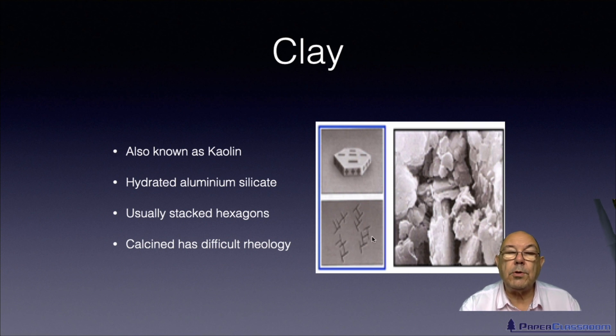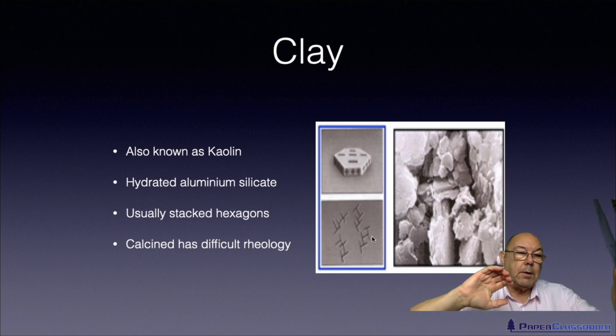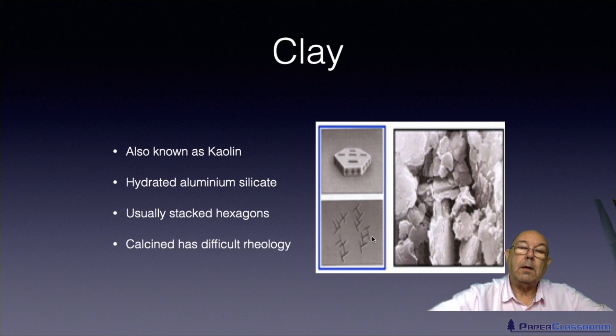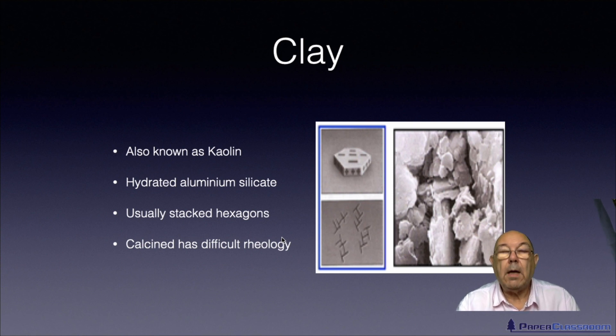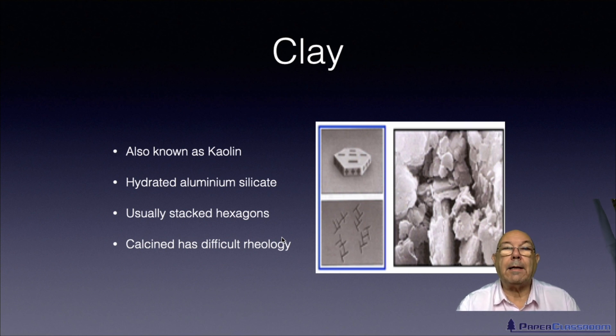The platelets fuse edge to face, and that causes huge rheological problems. If you imagine stirring this, the particles, because of their shape, want to lock into each other. And sure enough, the faster you stir a calcine clay slurry, the thicker it gets. If you stir it fast enough it will set like concrete, and then when you leave it alone it'll come back to being a slurry again. So there are tremendous difficulties in handling calcine clay slurries.